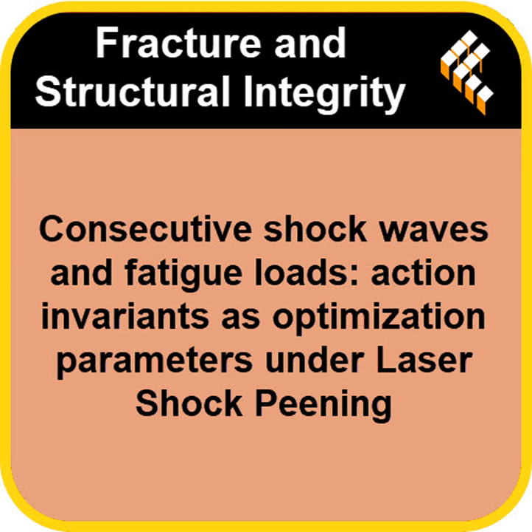Right before the main crack initiated and the sample failed, especially in the lower stress VHCF tests, this beta relative value would suddenly shoot up. An avalanche-like growth. Like the damage was accumulating quietly, then hit a critical point and cascaded. Exactly like that. It supports the idea of hitting a critical energy threshold, related to that fatigue action invariant A_F, which triggers macroscopic failure. Okay, so the mechanical test linked the shock invariant A_LSP to the fatigue life and this critical failure point.